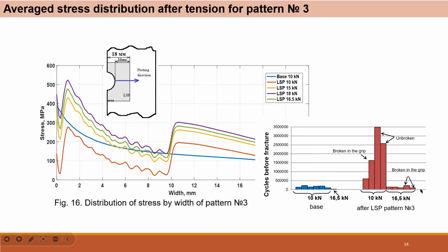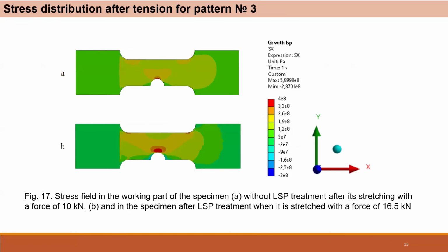And after that, when we increase the load for treated specimens of pattern number 3, we have the same fatigue life as for base specimens. So we proved our thoughts about this.